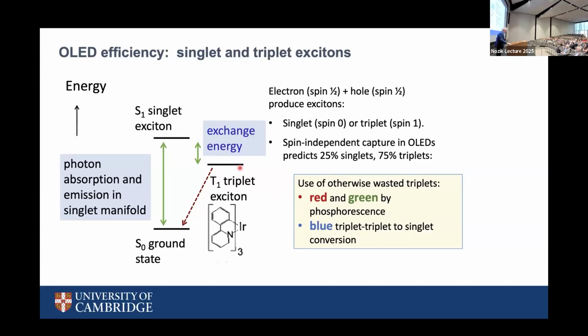What you have in your smartphone are 2 different technologies to do that. For the red and the green pixels, you have some iridium, or if it's a newer phone, some platinum in it. It's an organometallic complex that is the light emitter. And the heavy element has strong spin-orbit coupling. It mixes up what is singlet and what is triplet, so you get fast enough emission so that light comes out as phosphorescence with a lifetime of about a microsecond. That works quite well. It's not been engineered to work for blue yet, not quite.